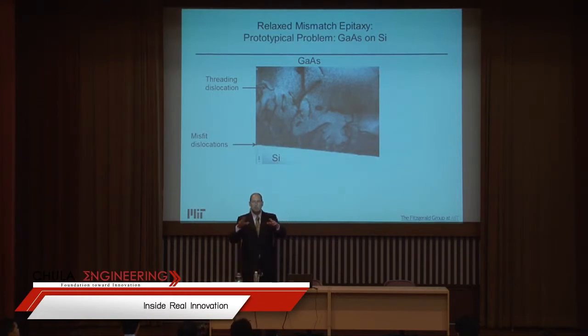You have to have misfits at the interface to relieve stress, but the threads that come up through there are actually part of the same thing. Those of you that are into material science know a dislocation can't end in a crystal. So even though you need the part at the interface to relieve the stress, the threading segments always have to come up. So this really means there's a nucleation problem, right? That's what you realize when you consider the theorem that a dislocation can't end in a crystal, and you need those misfit components. What you realize right away is that the number of threads that I have is connected to the number of nucleation events of the dislocation, because every time I nucleate a dislocation, I have two threading arms I have to deal with, right?